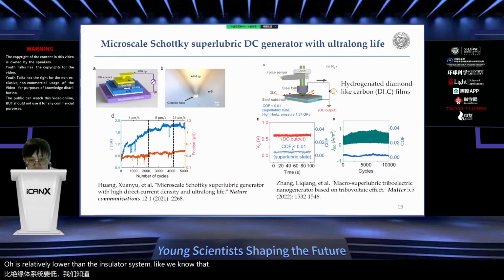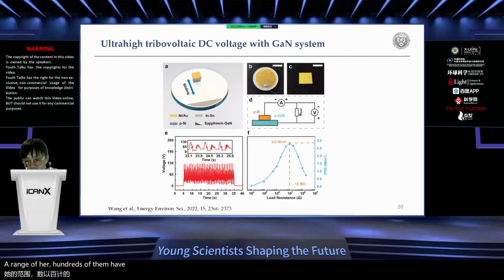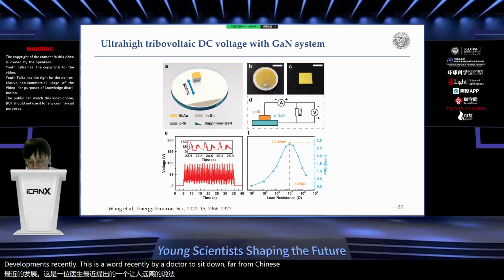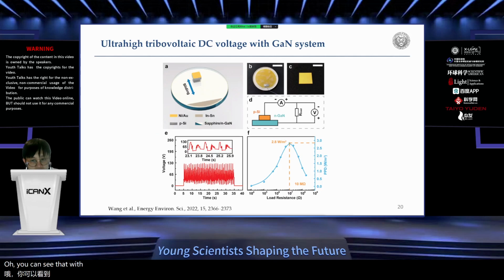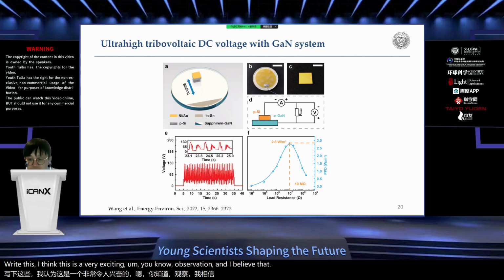And like we mentioned, the voltage of the semiconductor system is relatively lower than that of the insulator system. As we show here, most of these voltages are in the range of hundreds of millivolts. But there are some exciting developments recently, a work by Dr. Zhang from the Chinese Academy of Sciences. You can see that with some very special material systems, for example this N-type gallium nitride system, the sliding between the metal and gallium nitride can generate a surprisingly high DC voltage. This DC voltage can reach as high as 130 volts. I think this is a very exciting observation, and I believe there is much new physics underneath as well.